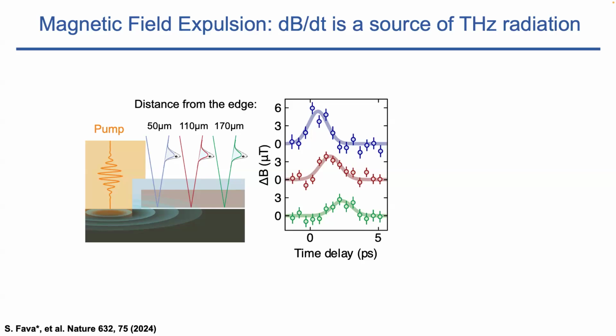I understand, but the gallium phosphide will have a polarization rotation that is proportional to B times the Verdet constant, which is a very small number. So a factor of 5 in B buys me a factor of, what is it, 25 in acquisition time. And this experiment takes maybe 5 days per curve. Come again? The problem is that the Faraday effect doesn't see fields in the plane. Remember the Faraday effect, you want a Poynting vector and the magnetic field along the same direction. So we're trying to get better, but this is where we are.